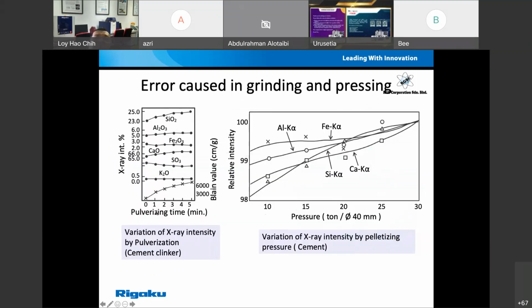Okay, so this is the error caused by grinding and pressing. Let's say for silicon oxide, if your pulverizing time is getting longer, then you can see that your X-ray intensity is getting higher and it will saturate at one point. But in certain elements like SO3, as you grind for too long, your concentration actually is getting lower and lower. And for calcium, it will get higher. Okay, this is the effect of the pulverizing time.